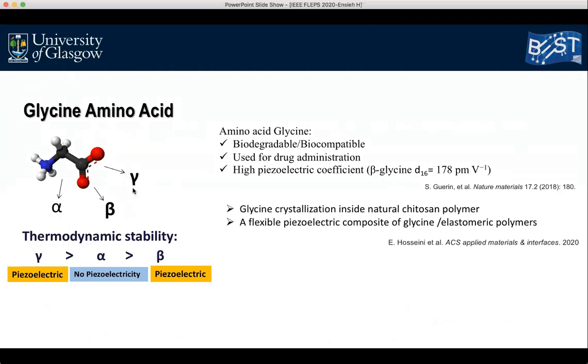Glycine can be crystallized in 3 different polymorphic phases. As I said, a high piezoelectric coefficient is observed in the beta phase. However, beta crystals are usually in the form of microcrystals, and they are thermodynamically unstable at room temperature and usually in a mixture with the other phase, mainly alpha phase, which is not piezoelectric. Therefore, not much has been reported on the application of piezoelectric properties of glycine beta phase.